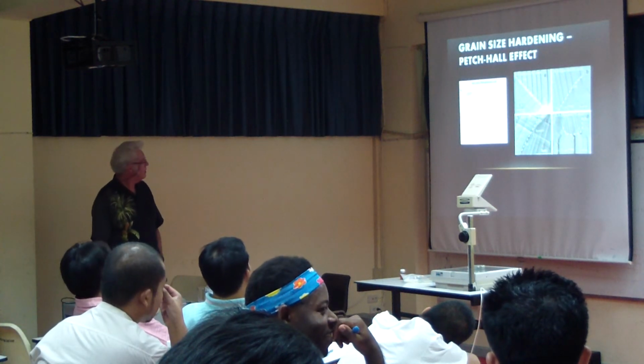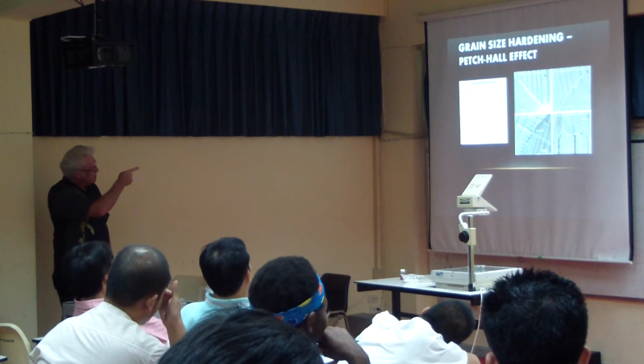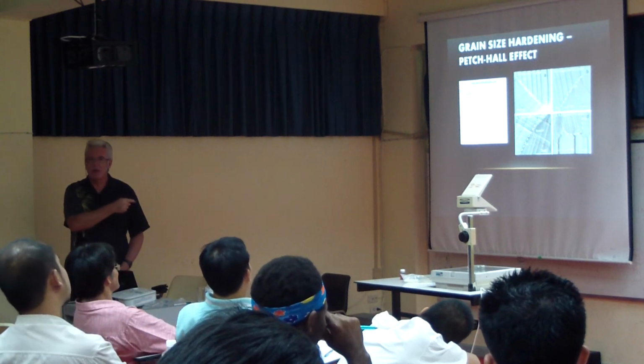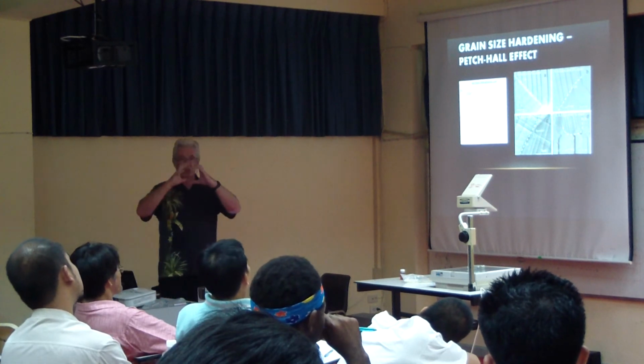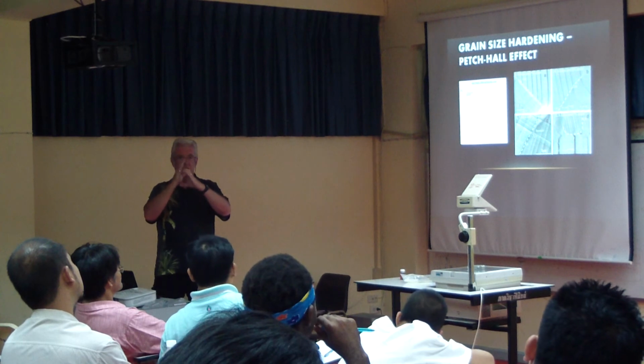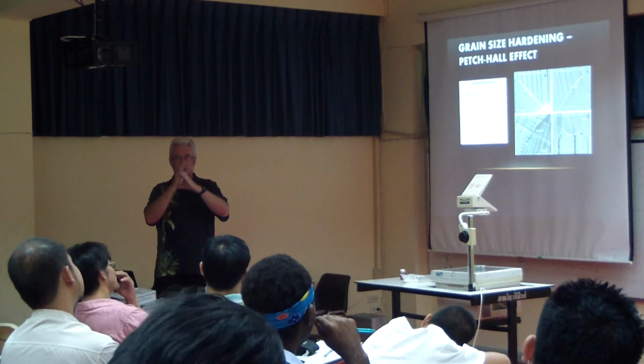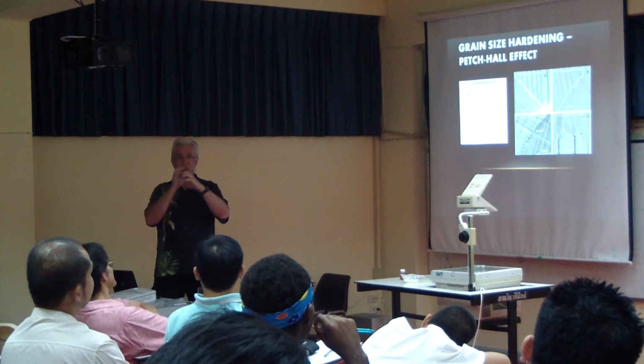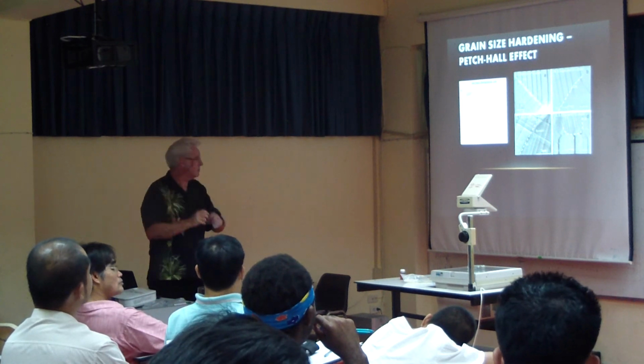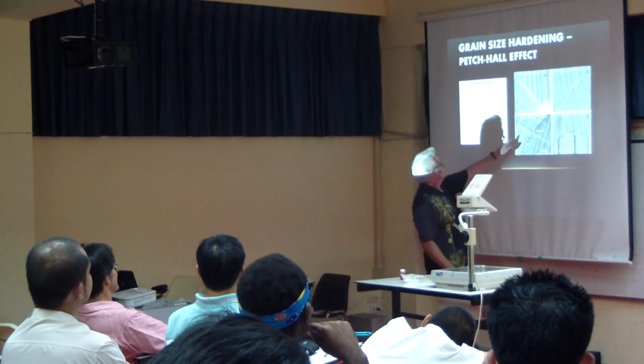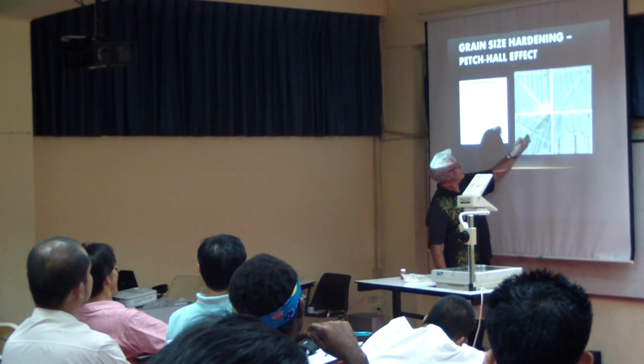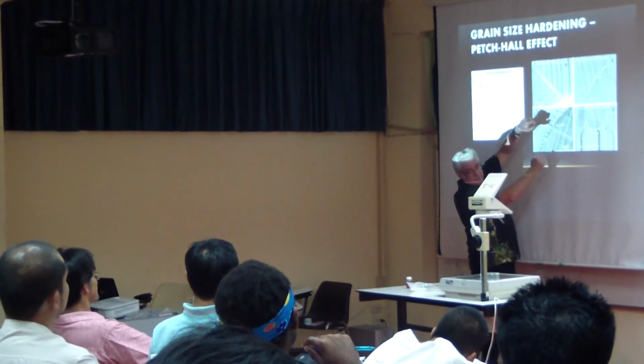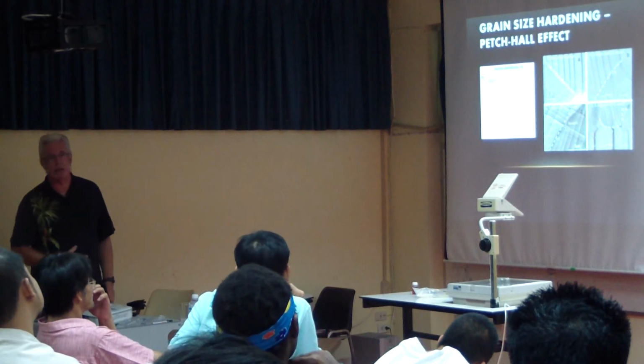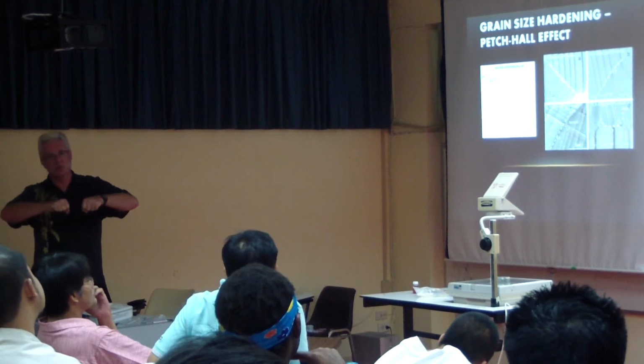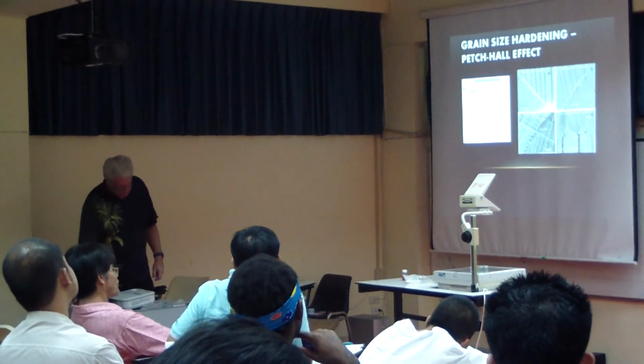The problem is that I get to a certain size and the strength drops off. And the reason is that as the grain gets smaller and smaller, the dislocations can't move much, so the structure says, I've got to move, somebody's applying the stress, and the grains start to move past one another. So you can see here, this is one grain, this is another, and this is what's called grain boundary sliding. Nonetheless, that can become very important because we can get what's called superplastic effects, where we can make these metals stretch like a polymer. So that's important.